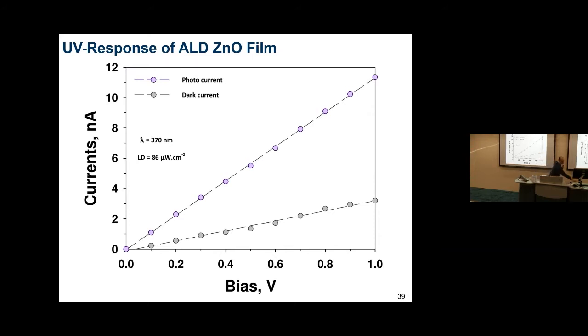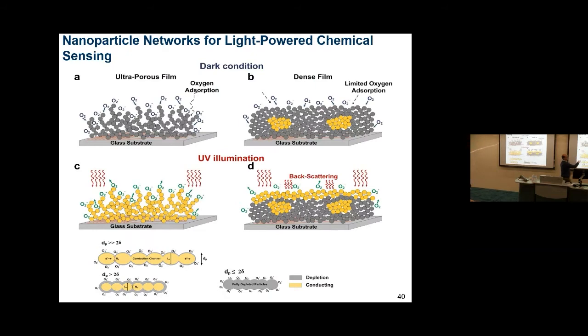And the reason is that the structure matters. Once you get this porous structure, you can adsorb and desorb oxygen, almost similarly to a chemoresistive sensor, and therefore you activate all your material, giving you this huge change in current.